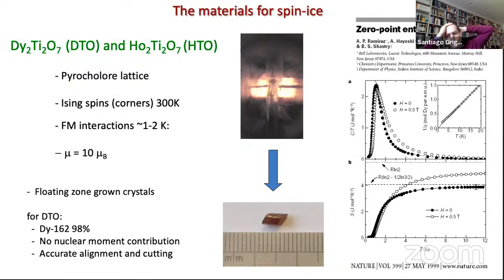Okay, so what people did for spin ice is the same thing that people did for water previously. So I think it's a paper from 1933, Giauque, who measured specific heat for ice, integrated it out, and saw that there was a missing part. So if you assume that you start from 0 entropy at 0 temperature, you see that you don't reach the entropy expected, which is essentially R log 2, and the missing bit corresponds to the residual entropy. Right, so people did exactly the same thing for spin ice. This is a work by Ramirez in 1999, and you see that the residual entropy is very well described by Pauling's entropy.